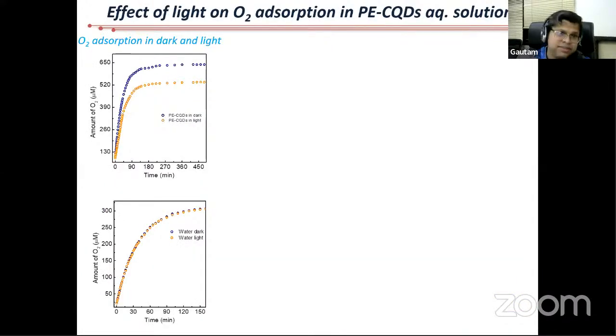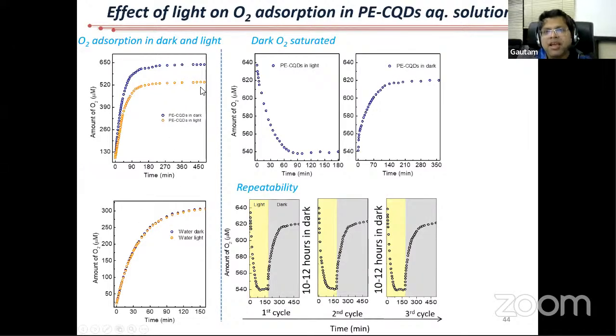And you can look at this. If you look at the saturated levels of oxygen, the number is 520 in light, and in dark it is 650. So you can see a drastic change in the level of oxygen. You do not see the same, there is no change if you just take pure water. Both the plots overlap, but here you see that it is different. And here you can see that this is actually a reversible process. Light, dark, light, dark, light, dark. So this keeps happening.